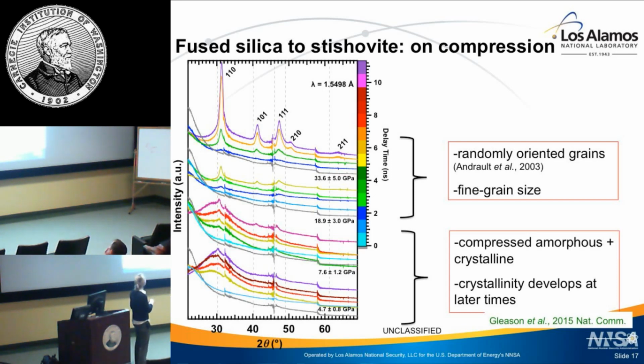Higher pressure, so 34, 20 GPa, we notice almost immediately we see our peaks corresponding, or that I've indexed to stishovite, they come up very, very quickly, so early time delays. And I see pretty much only crystalline. There's no superpositioning of any other features, so it's just crystalline material. And you could say, having some background in diffraction, the peaks are sort of broad, right? So the grain size is fairly small.